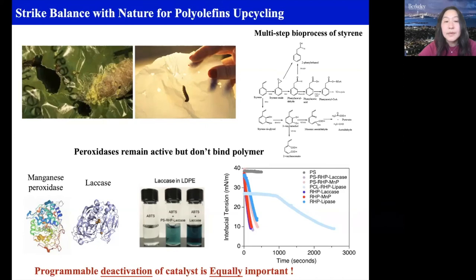What we did is we tried to figure out why it cannot be oxidized or modified. So we embedded several different varieties of peroxidase that people claim in the literature. The good news is that many of them remain active inside the plastic. They can generate active radicals and react with small molecule substrates, no problem on that front. But we modulated whether this radical can access the substrate, and all the results show that the radical can be generated, but eventually it just decays. They don't really access the substrate.